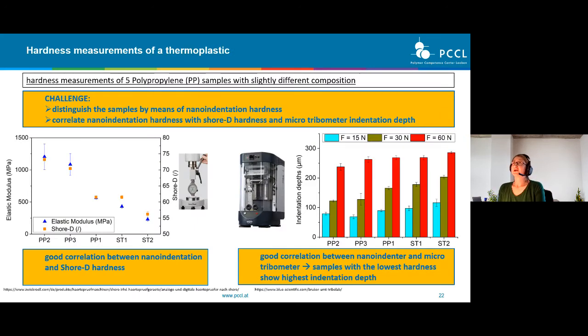We also did hardness measurements of 5 polypropylene samples with slightly different composition. You can see here on the left side in blue, we did nanoindentation to get the elastic modulus, and also Shore D hardness measurements in orange. For these 5 samples, the elastic modulus and the Shore D hardness are correlated to each other. So we have a good correlation between nanoindentation and Shore D hardness.